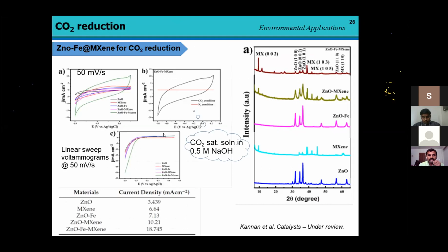Then recently, there was one group from India who is working abroad. They have also tested carbon dioxide reduction using MXene-based material. They developed some metal oxide, bimetal oxide, on the MXene phase. They successfully delaminated the MXene sheet to get nanosheets. They tested it towards carbon dioxide reduction. From cyclic voltammetry, they found a current density of 18.745, which is much higher than the other materials developed for this study. Then they utilized a carbon dioxide saturated solution in 0.5 molar sodium hydroxide.